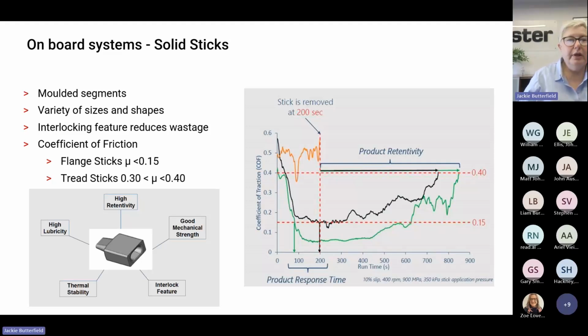So again, we're looking at key characteristics for sticks. So we need a high lubricity, particularly for flange sticks. So we need that low coefficient of friction. We need a high retentivity. So we want the stick film to last a long time in that wheel rail interface, so that the stick consumption rate is kept low.